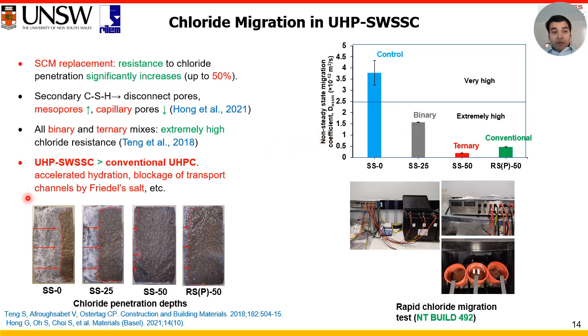We can also see this from the rapid chloride migration test, where almost 3/4 of the depth has been penetrated by chloride in the control mix, whereas in the 50% SCM based ternary mix we barely can see any chloride front.